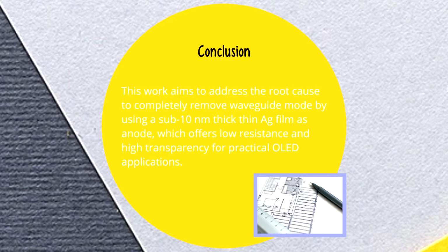The total thickness of the OLED is maintained thinner than the cut-off thickness for the formation of an optical mode of the layers, thereby suppressing the waveguide mode in the device. This simple and yet novel approach could pave the way to replace ITO and increase efficiency in flexible and transparent OLEDs that are widely used in the display industry.